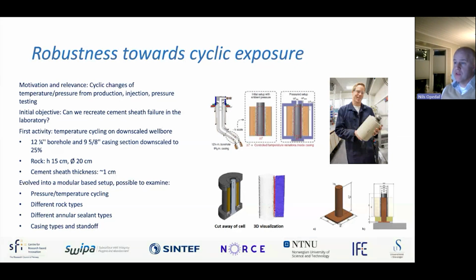So the initial objective was, can we recreate cement sheath failure in a laboratory, meaning in a controlled setting? So we should somehow be able to manage this in a laboratory setting. The first thought process was, how are we going to downscale this to a manageable scale, but still large enough to be somehow relevant? So we took inspiration from a 12.25-inch borehole with a 9 5/8-inch casing, downscaled to about 25%, or a quarter, of its value. That gives us specimen dimensions of an outer rock with a height of 15 centimeters and a diameter of 20 centimeters.